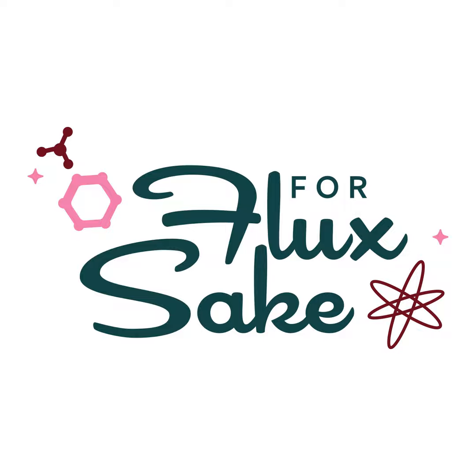So the problem with using the iron-based sources is that iron is really going to melt effectively into that glaze. And in fact, I just had a student testing that and looking at variations in a glaze using ilmenite. So anyway, granular manganese, that makes sense for everybody. That's just manganese. And when we say granular, we're really talking about mesh size. I don't think there's a specific mesh size that needs to be listed for it to be designated as granular. Oh, yeah, that I don't know, but it's probably a 40-60 or something. It's definitely less than 100.